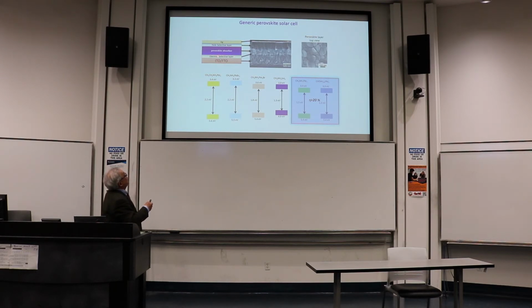Instead of putting the titanium oxide, you just put the perovskite absorber. This is an SEM image, the scale is 500 nanometers. They look like little crystallites. They're not very beautiful, it's a dark film. And this shows the different colors of different types of perovskite. The iodine perovskite is dark brown, and it gives the highest efficiency. We work with nearly transparent, which is bromine.